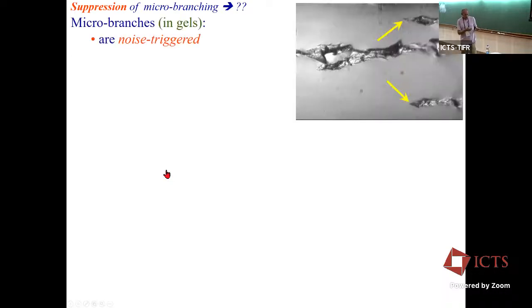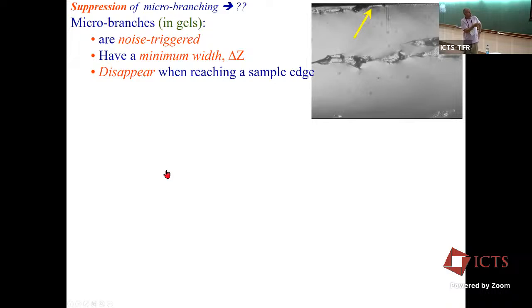Now, empirically, we can suppress crack branching in gels. And how do we do that? Because gels are basically noise triggered, these instabilities. So these are the micro branches. They started here because the crack front, which is moving through the material, got kicked here and here, so they started. Now, they have a minimum width to them. They don't expand over the whole surface, each one of these lines of microscopic branches. And when one of these hits an edge, this is a free surface, they disappear.